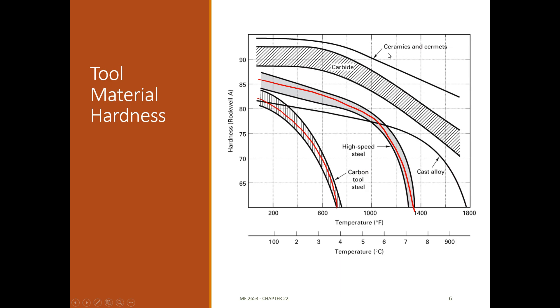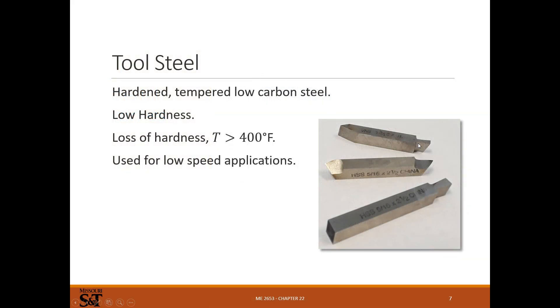Carbides appear somewhere between a metal and a ceramic. They have a higher hardness and keep their hardness as they get hot. Then we have full-on ceramics and cermets way up at the top. But all these materials suffer as they get hotter — some just suffer less than others. Tool steel and high speed steel are different things: tool steel we don't use for machining much because it gets soft around 400 degrees. High speed steel is about a hundred years old, has special alloying elements that keep its hardness up to around 1100 degrees, which makes it suitable for machining — about two to three times the cutting speed of tool steel with equal tool life.